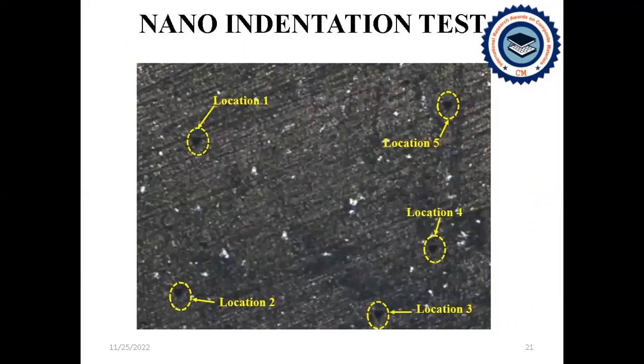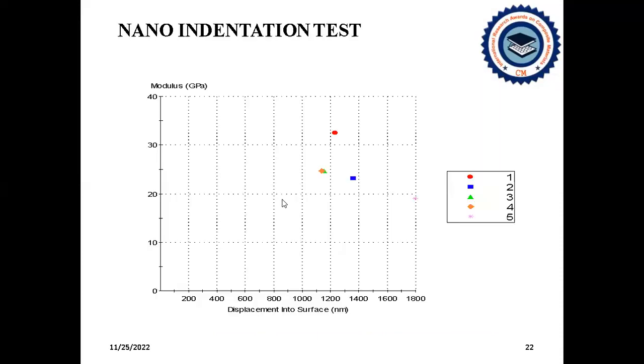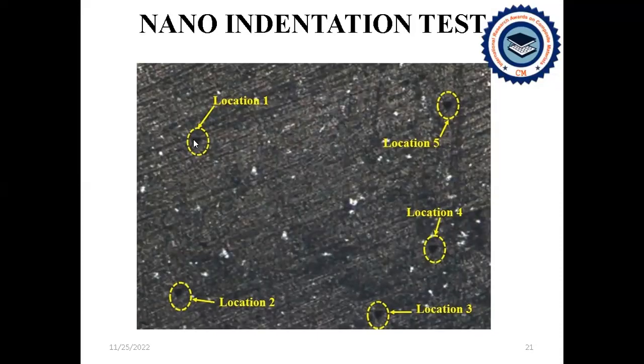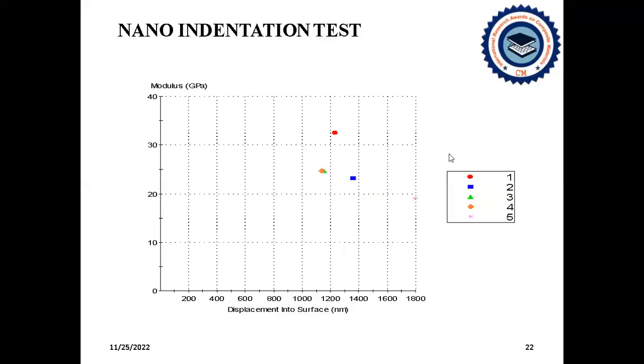And the nano indentation result, when it comes to the nano indentation test, this micrograph represents the Berkovich indenter mark that is present on the sample where the indentation test was carried out at location 1, location 2, location 3, location 4, and location 5.